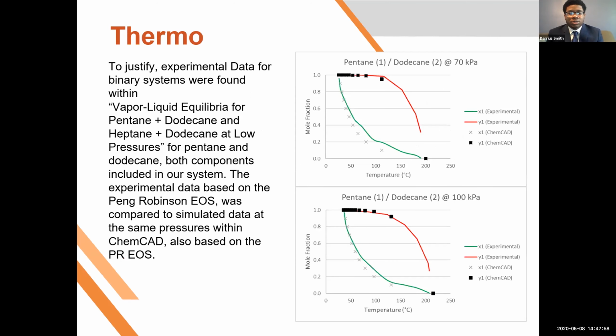Next slide, please. As you can see, we found systems of pentane and dodecane, which are both components found within our system, at atmospheric pressure and below atmospheric pressure, since we might be using vacuum distillation columns. The black dots and the gray X's represent our simulated data from ChemCAD, which corresponds to the green and red lines, our thermodynamic data from literature. Since the curves are pretty much lined up, we decided to use Peng-Robinson as our thermodynamic model.